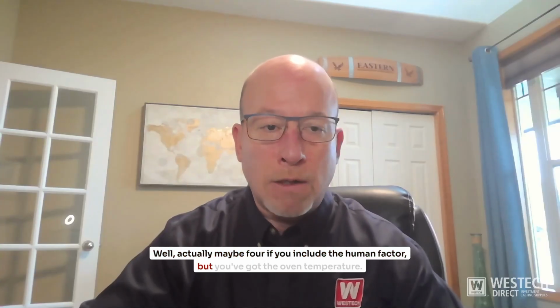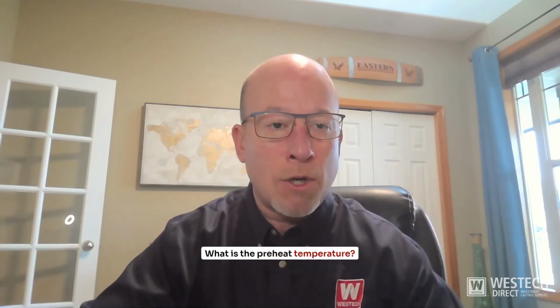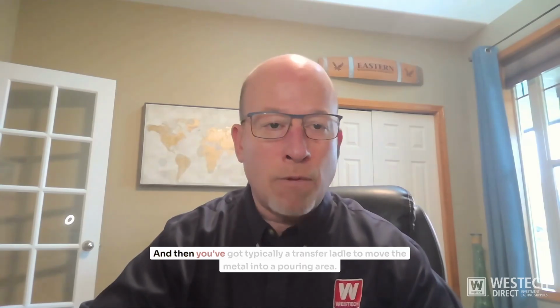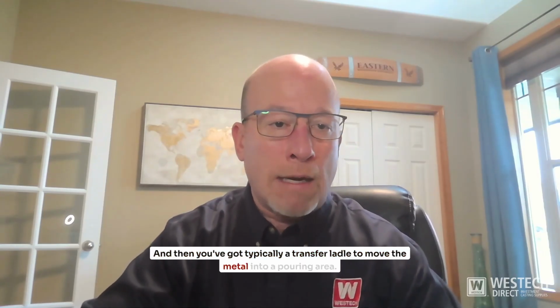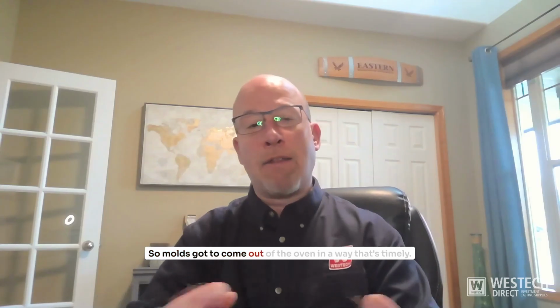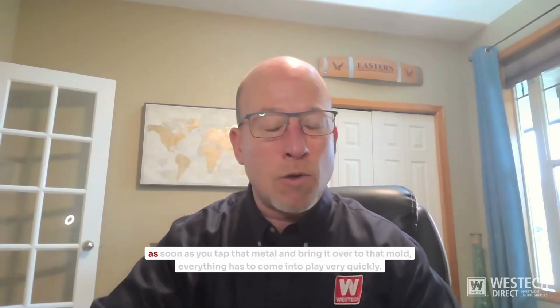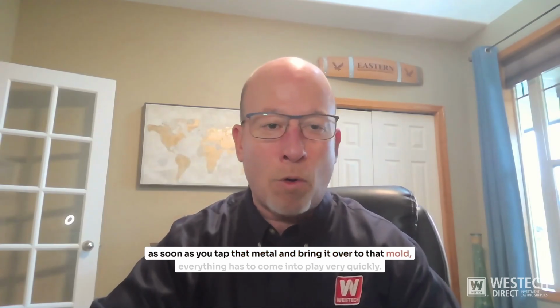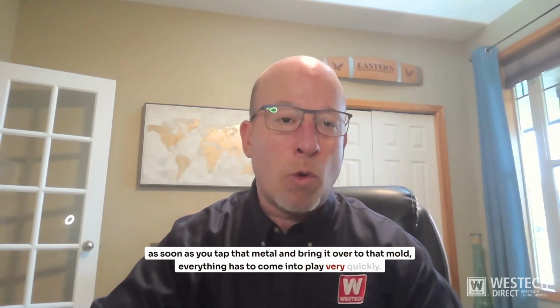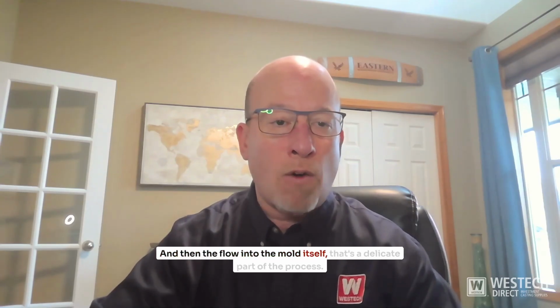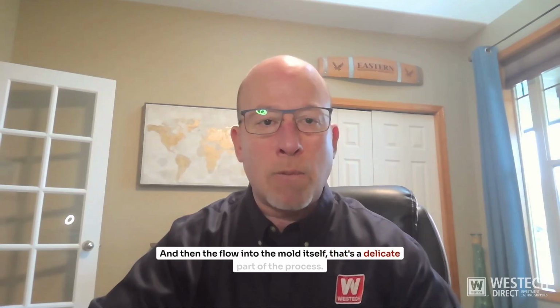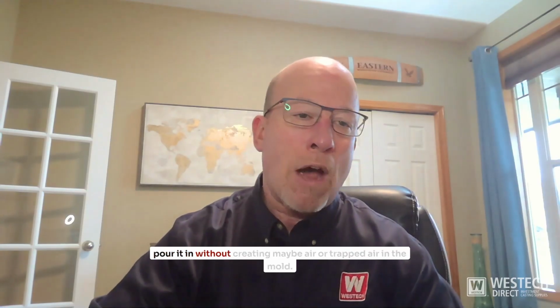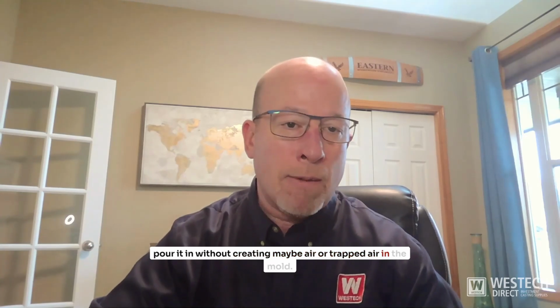Every time I think of the pouring area, it's an orchestration. You've got three different factors. Well, actually, maybe four if you include the human factor, but you've got the oven temperature. What is the preheat temperature? What is the pouring temperature? And then you've got typically a transfer ladle to move the metal into a pouring area. So the mold's got to come out of the oven in a way that's timely. As soon as you tap that metal and bring it over to that mold, everything has to come into play very quickly. And then the flow into the mold itself, that's a delicate part of the process. Pour it in without creating maybe air or trapped air in the mold.